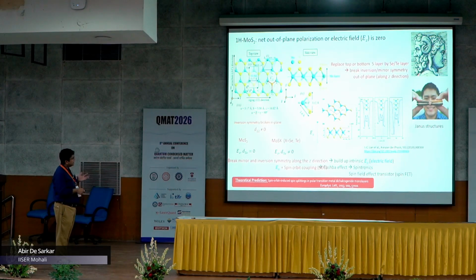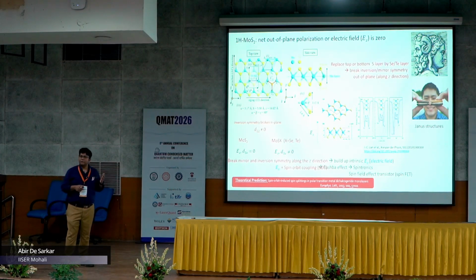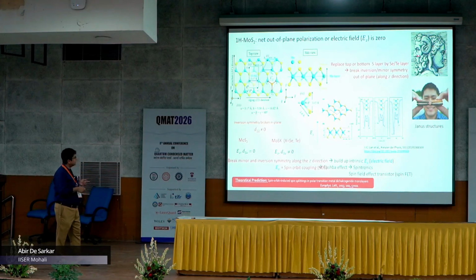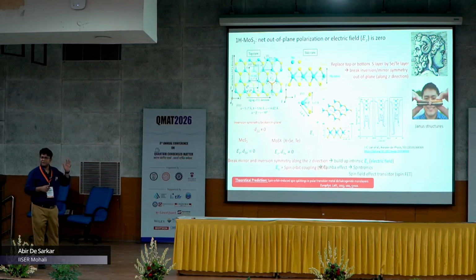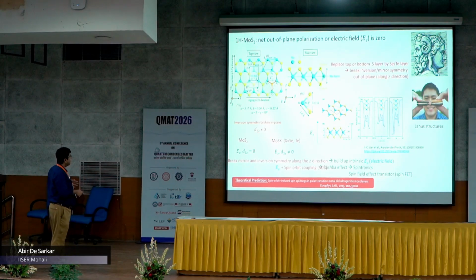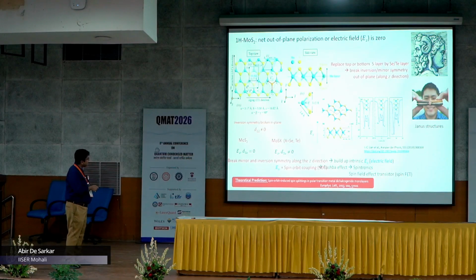The word Janus is derived from the Roman god Janus, who has two different faces. In this case, if you replace the top layer of sulfur by a layer of selenium, you can convert this into the so-called Janus structure. As you turn this into the Janus structure, the inversion symmetry is broken along the z direction, for which an out-of-plane piezoelectricity arises. And also the formation of the Janus structure introduces an asymmetry in the crystal potential, as we can observe over here.